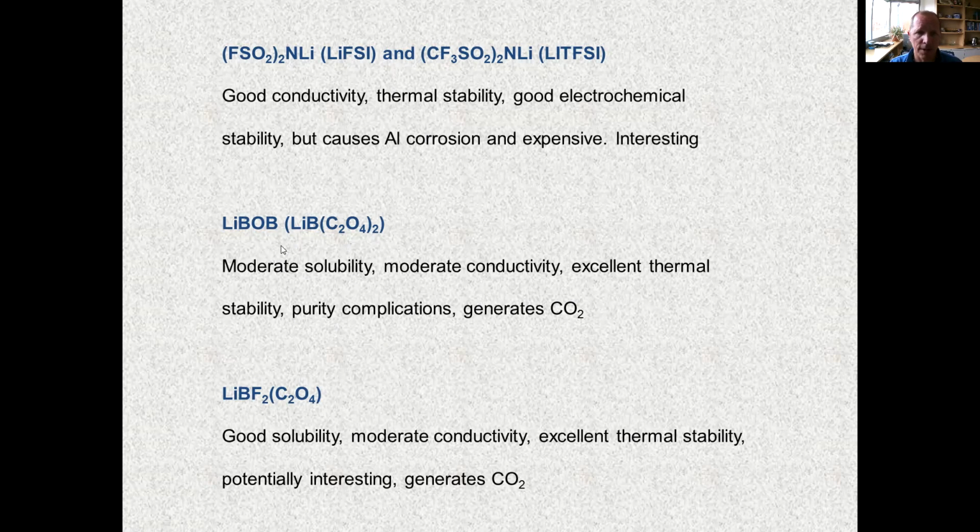A better salt than LiBOB is lithium difluorooxalatoborate, frequently referred to as LiDFOB. This one has very good solubility, much better solubility than LiBOB, moderate conductivity, very good thermal stability. I would say it's once again a potentially interesting salt. It's got some problems. Once again, it also generates CO2 from the oxalato ligand, but I think it has as much promise as LiFSI and LiTFSI.